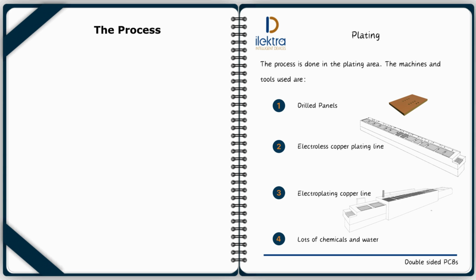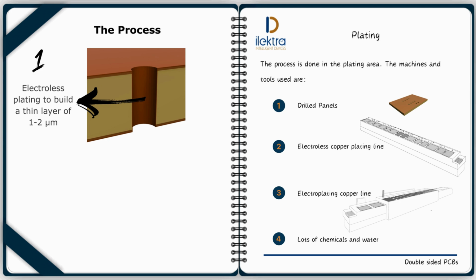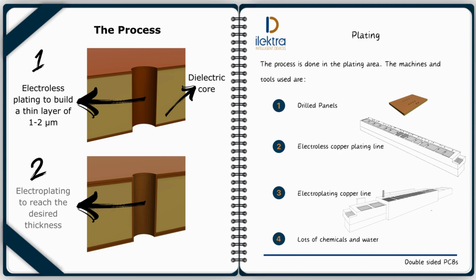Copper buildup is done in two steps. The first is to use the slow electroless plating method to deposit a thin layer of copper on the surface and the walls of drilled holes. Then, when all surfaces are made conductive, the much faster electrolytic plating, or electroplating, immediately follows to reach the desired copper thickness value. Their major difference is that electroplating needs electricity, while electroless does not.